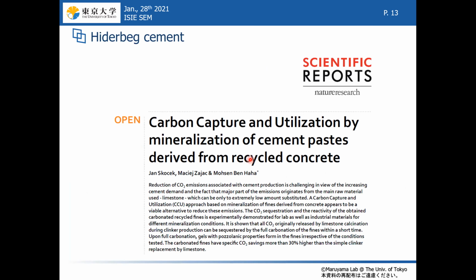The other method is proposed by the Heidelberg Cement Company. As I mentioned, calcium and silicate are very important materials for construction. These materials can be found in glassy materials and byproducts. First, they mix these materials with ordinary Portland cement and then wait for a long period to make the reaction inside. After that, to capture the CO2, after demolishing the concrete structure, they try to make a reaction with the CO2. We call it carbonation.